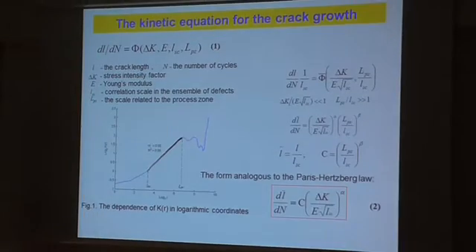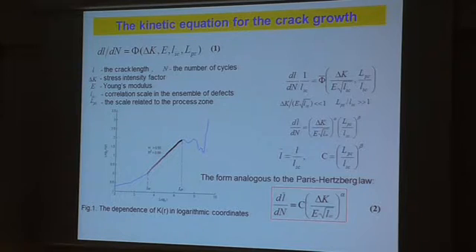It's the technique of the processing. And it was very important for us because there is an open question how to modify Paris law for typical high cyclic fatigue area with very pronounced scaling phenomena at the power in the delta K. That is fantastically deep results for the case of small cracks.